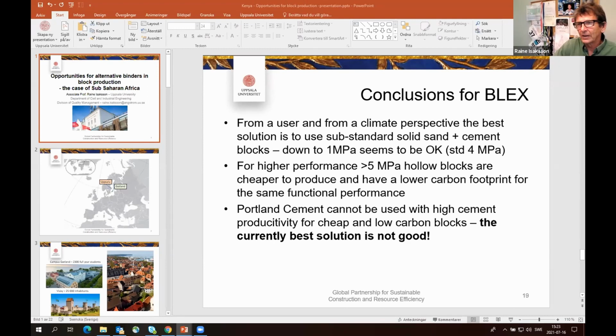And down to 1 megapascal seems to be okay. Research is missing here. What is really needed? A 1 megapascal block, 6-inch block, still could carry 6 tons. So if it's put well in place, the compressive strength should not be a problem. Then the durability, well, research I think is missing. Standard requires 4. So for higher performance blocks, when we go to government projects or where they do the measurements, where we need to fulfill the standards, then hollow blocks normally would be a better solution, which gives you both a better price or lower cement consumption per square meter of wall and lower carbon emissions per wall.